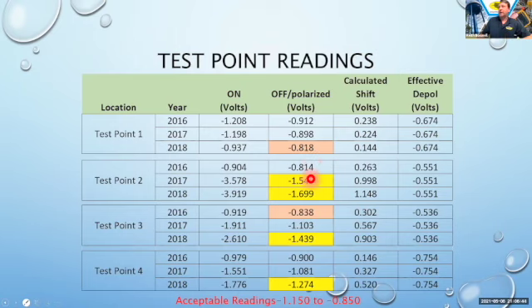I have a few other cells highlighted in yellow here that are pretty excessive as far as a polarized potential is concerned. There have been studies performed within the industry, and for steel it's empirically not possible to polarize steel to a potential more negative than 1.15 volts. So when we see readings like this, where they're excessively more negative than 1.15 volts, that leads us to believe that there's probably some error in that measurement that is causing that excessive potential.